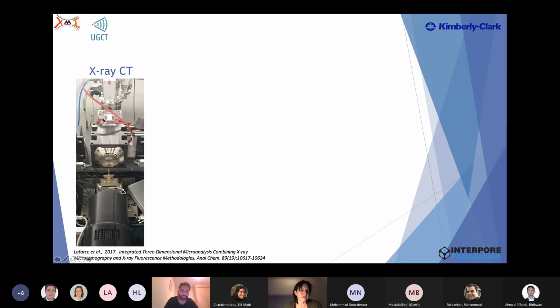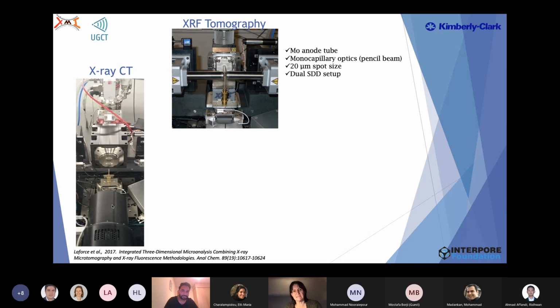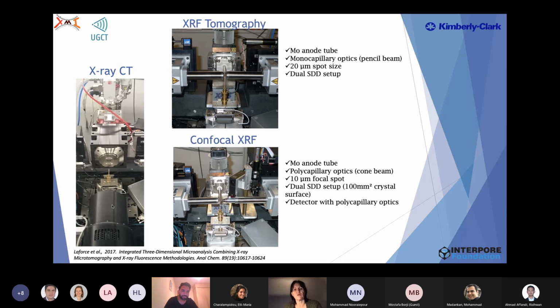So here you see the CT system. This is the source, and here you have one of the detectors available for X-ray detection. Then we have two end stations, one for XRF tomography and one for confocal XRF, and depending on which end station you use, you have different resolution. In the confocal, we have a focal spot of 10 microns; in the XRF tomography, a spot size of 20 microns.